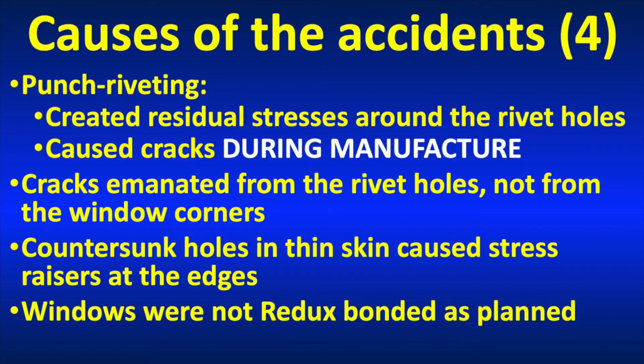Now, originally, de Havilland was going to use Redux bonding around the windows, and I'll have a look at that in a moment. They had experience of that with the de Havilland Dove fuselage and also the de Havilland Hornet, but they decided that it was too hard, because this stuff is a kind of glue, and you've got to heat it to about 140 Celsius and then hold it under high pressure while it cures. So they said, well, to hell with this, we're just going to rivet the windows because it's too hard to use the Redux. So the riveting technique they used was called punch riveting.